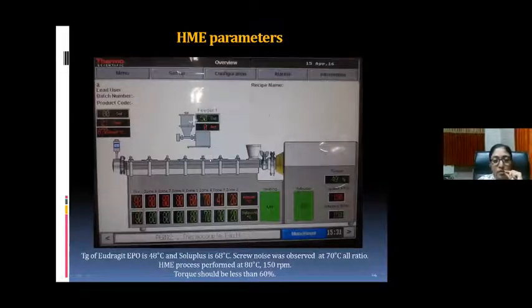Also, optimization of the temperature was done. It was observed that at 70 degrees Celsius, there was certain noise for all the different HME concentrations that were prepared. That is why we optimized the temperature to 80 degrees Celsius, and the whole HME process was carried out at 80 degrees Celsius at 150 RPM. The glass transition temperature of the two polymers was observed to be 48 for Eudragit EPO and 68 degrees Celsius for Soluplus. So near about that temperature, the molten mass forms at this area at about 80 degrees Celsius, and the screw elements push the material forward, which comes out in the form of a strand.